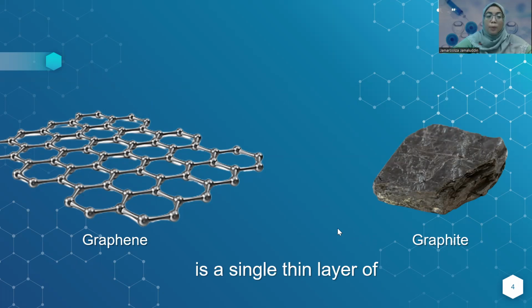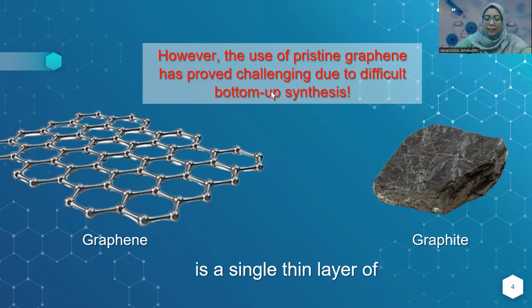While graphene's properties are incredibly promising, its use in practical applications has proven to be a challenge due to the difficulties in synthesizing pristine graphene. One of the biggest challenges in synthesizing graphene is achieving a high degree of structural perfection. For your information, graphene is very sensitive to defects and impurities, which can significantly degrade its properties.